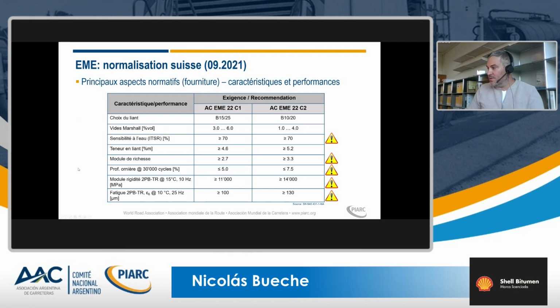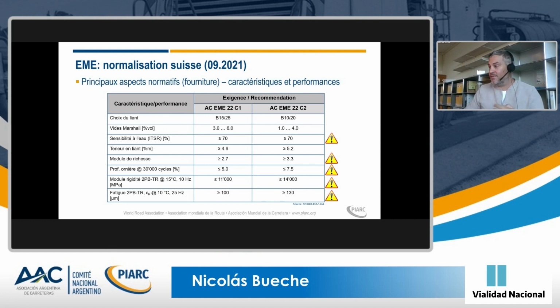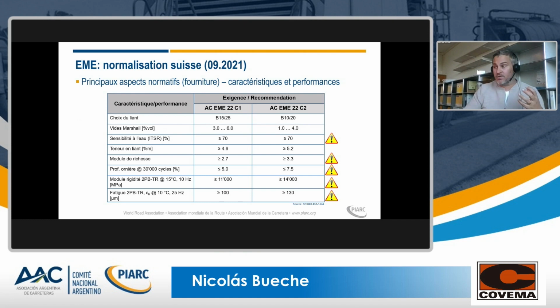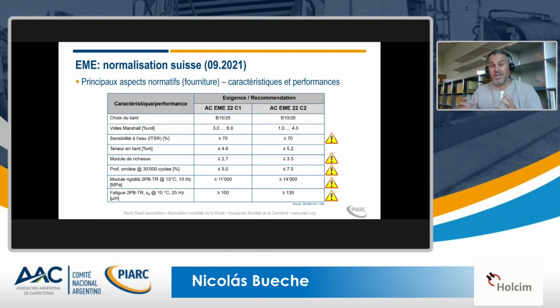But what is interesting, we have rutting resistance, French rutting tester, so maximum 5 or 7.5%. We need a high stiffness, 11,000 or 14,000 megapascal, and very high fatigue properties, which is a bit of a tricky point. Working with high modulus asphalt, you have to, on one hand, get high stiffness, but on the other hand, have good fatigue performances. And what you can find in this table is basically a summary of what we have in our national standards.